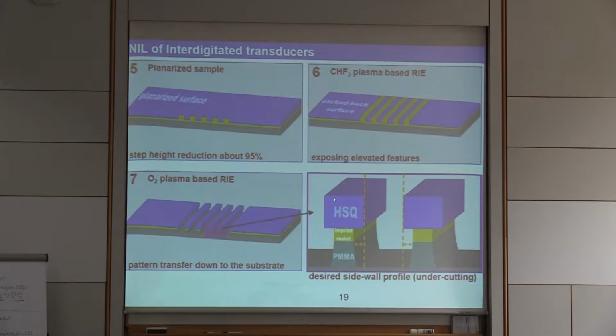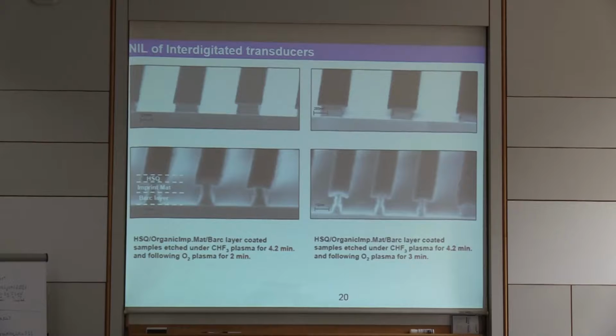So critical dimension is maintained, and finally this undercut feature allows you to do metallization and lift-off much more easily than if you would use the direct processing. So that's very advantageous, and probably one of the key factors why we can get to such high quality IDTs using this method. So here you see a number of SEM images